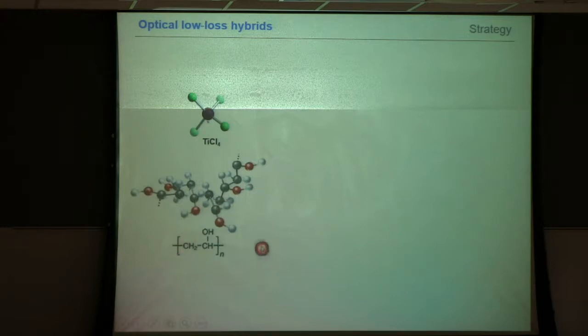So what did we do? Well, not being chemists, we simply thought, okay, why don't we just use a bulk commodity polymer, polyvinyl alcohol, often used, actually all Coke bottles have a polyvinyl alcohol coating, it's a derivative on it because it's a very good oxygen scavenger. So this we can buy in any molecular weight, so any chain length, and we just added, very similar to the paper I showed, a titanium dioxide precursor.